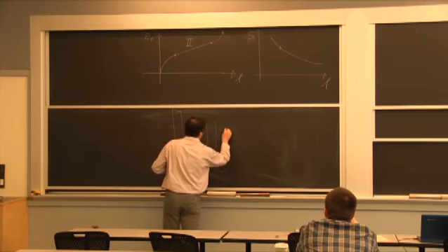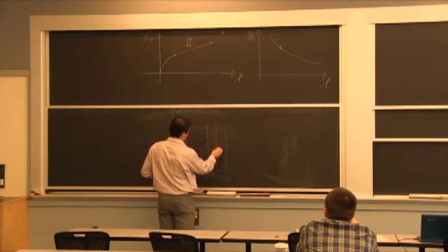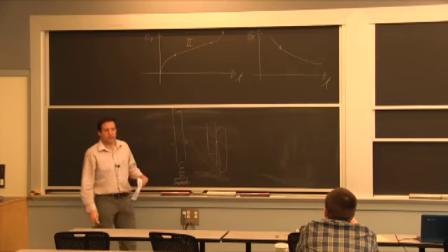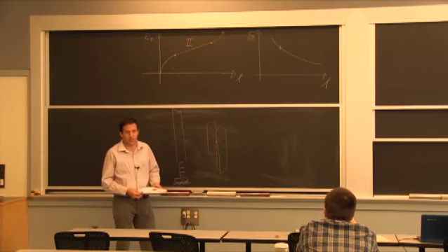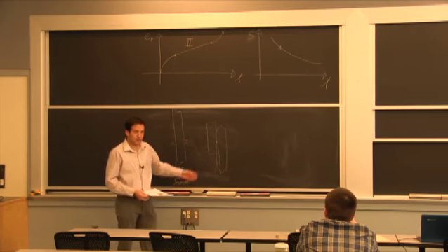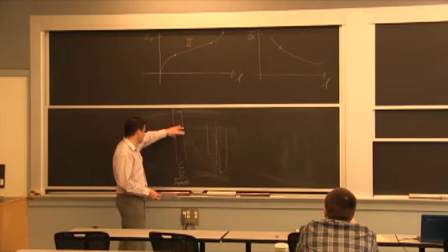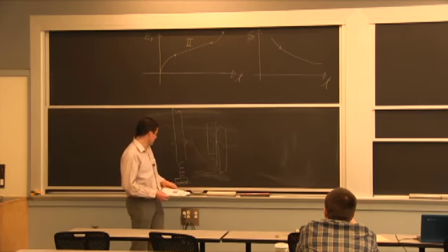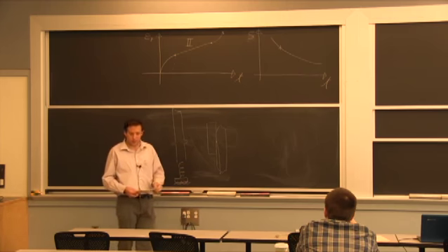So if I try to deform this, I really have a greater distance to go from taking the material here and putting it to the tip. So it's a greater distance than if this is equiaxed of the same size. And you can make these bigger as well. It's easy to make them directional by a temperature gradient here. They compete with each other. So instead of having the selector, you start here and they just compete and keep growing.